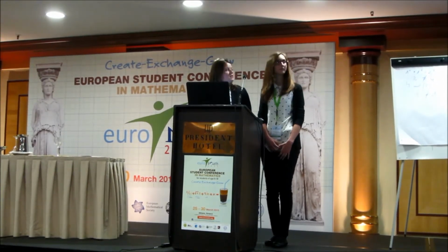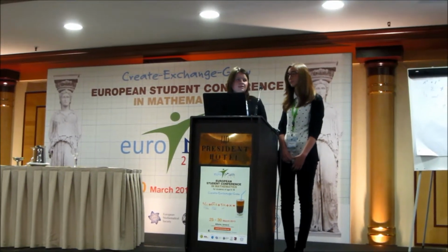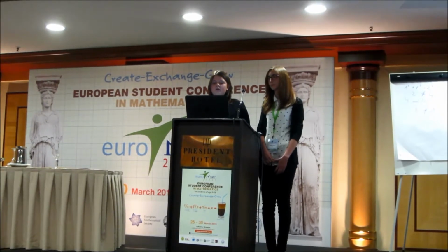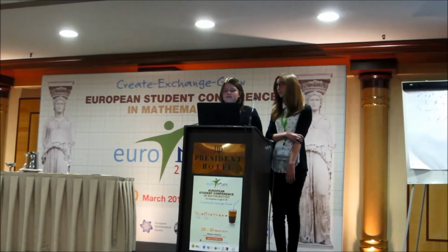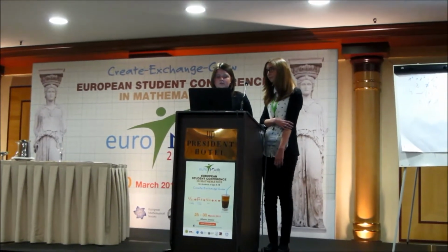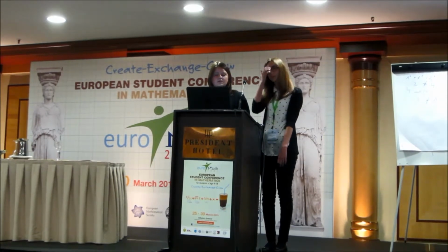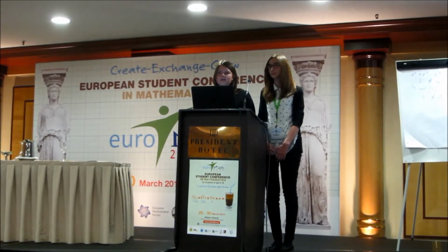On this slide you can see the Kissinger-Akahira-Sunose model. In this model, beta represents the heating rate, g of alpha represents the function of the reaction model, and T represents the temperature of the maximum speed of the reaction. R is the universal gas constant, A is the pre-exponential factor, and EA is the activation energy.